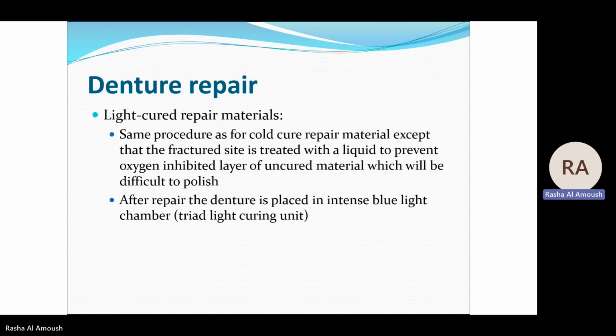We can also use light cured repair materials, with the same procedure as chemical cured, except that the fracture site is treated with a liquid to prevent an oxygen-inhibited layer of uncured material, which would be difficult to polish. After we repair, the denture is placed in a light curing unit to allow curing of the acrylics.